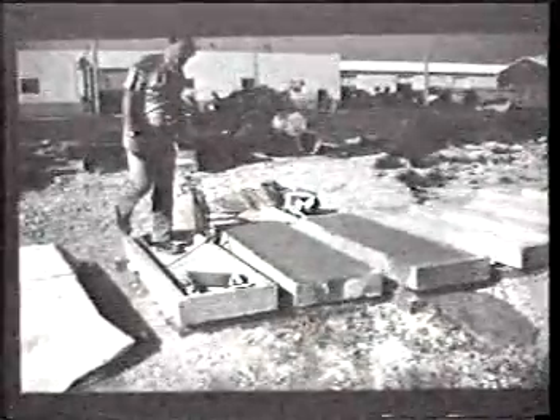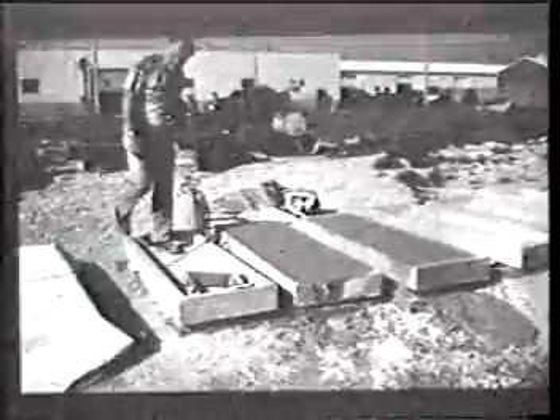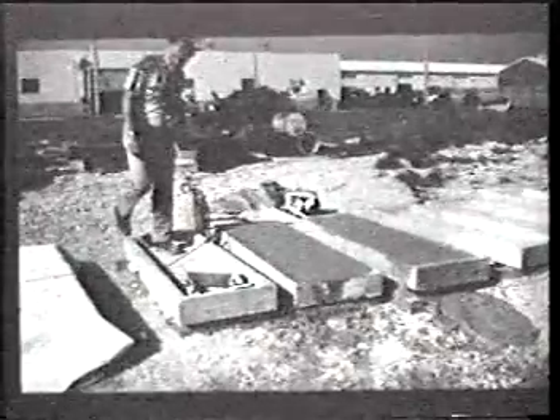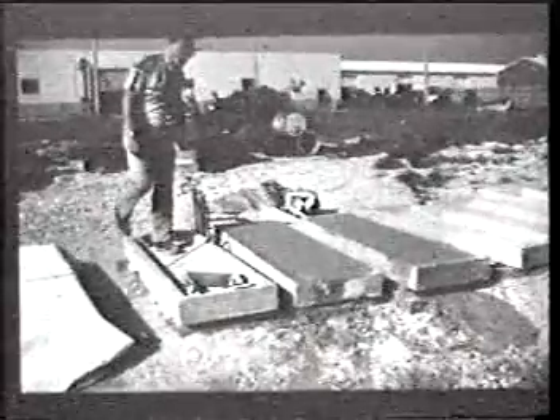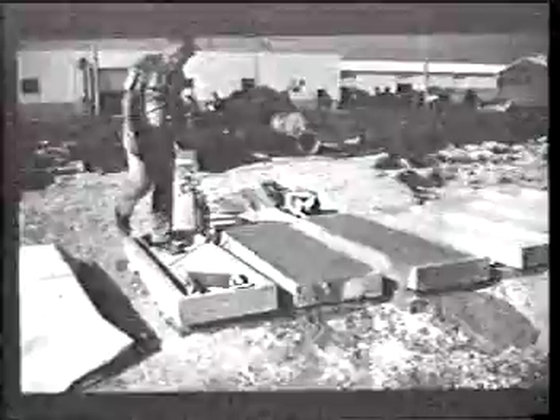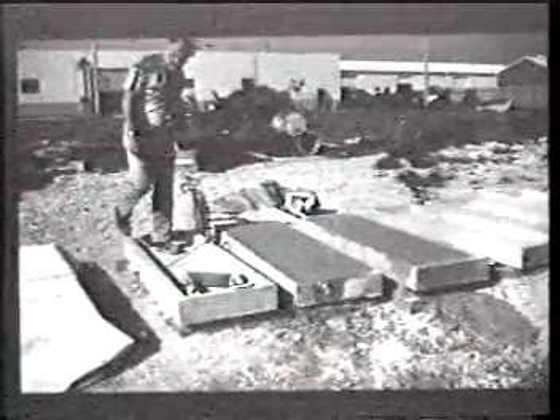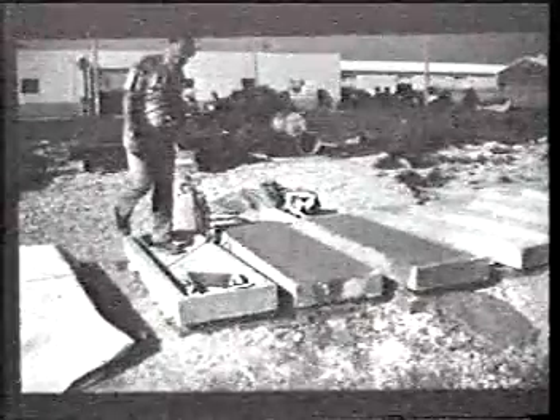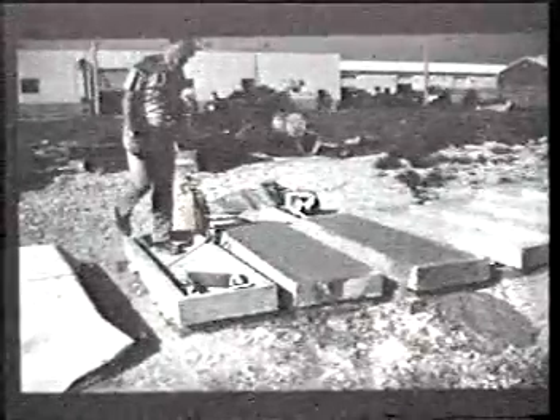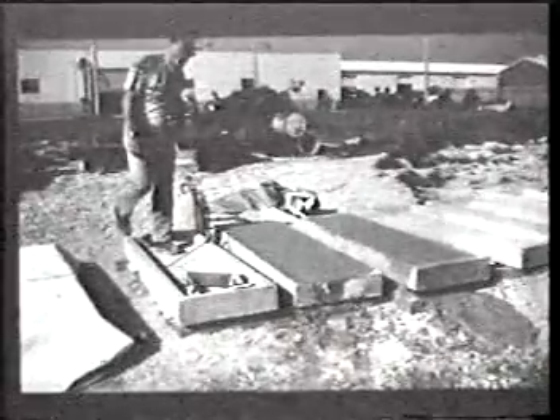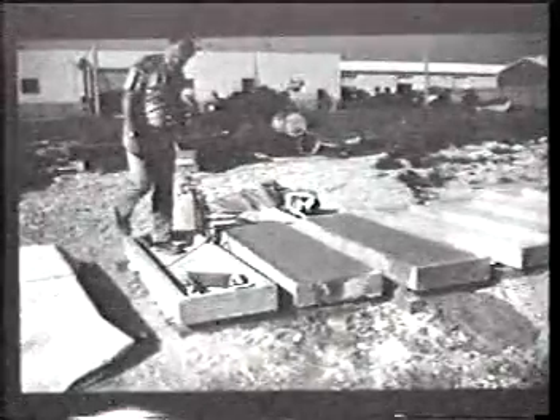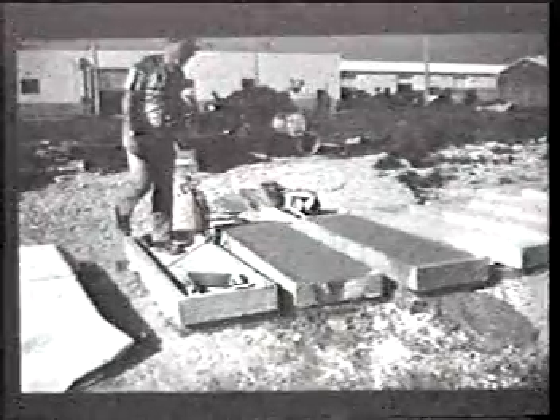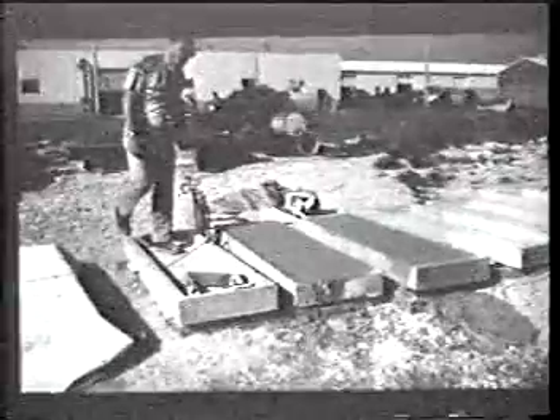These are the slabs we were testing, for your information. Yeah, we had very, very good quality control. You should imagine that we're going to speak about our industry. This was the case. This is Jim McDonald checking it. We had 3 chiefs for each Indian who was working on it. So it was a strict quality control, which we never have in the field. Also notice that we never have in the field such a smooth substrate as we have here, and almost from a practical point of view, the repair surface and the substrate were parallel, which we never have in the field.